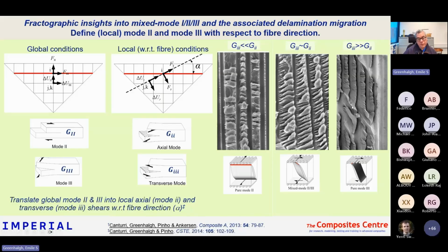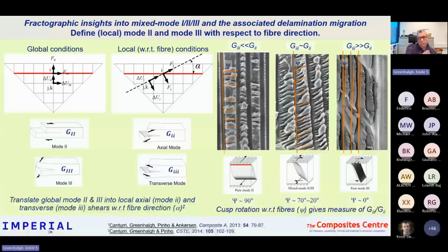And if you get to a mode 3 dominated condition, which is where migration occurs, so this is actually often a transition region within the material, it will start to develop these sorts of fractographic features, and then it will migrate into a new interface. Under those conditions, the cusps are parallel to the fibers. So this angle, as illustrated here, actually gives a measure of the local II/III ratio.